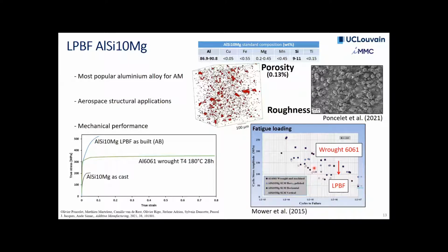Well, we have certainly improved the porosity levels in these materials, and so improved the fatigue resistance. However, we're still well below the raw alloys. And what's the reason for that? This is a commonly known fact in people working on fatigue resistance. Well, they know that porosities, and in particular large porosities, are actually a source of initiation of fatigue cracks.